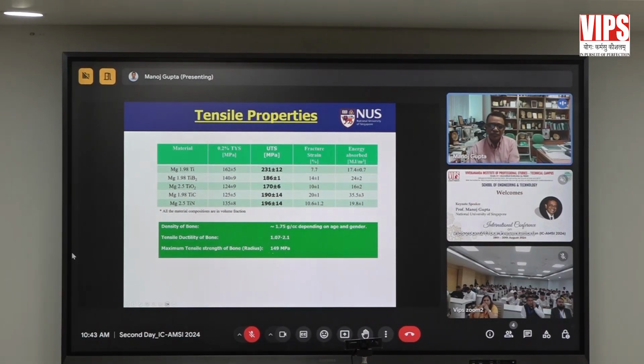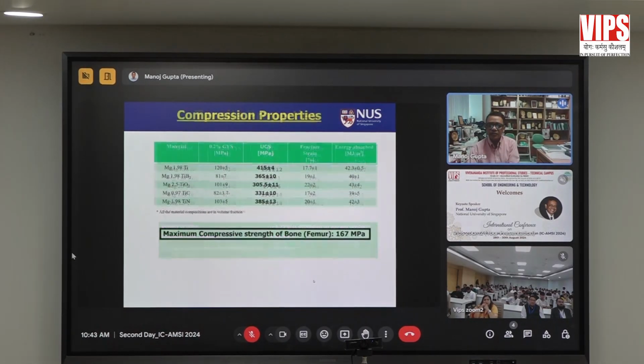And we compared with the strength of the bone. The maximum strength of the bone is 149 megapascal, and all our strength levels were higher than that. Then we also tried to look at the compressive properties, and once again the compressive properties were much higher than the strength exhibited by the bone.